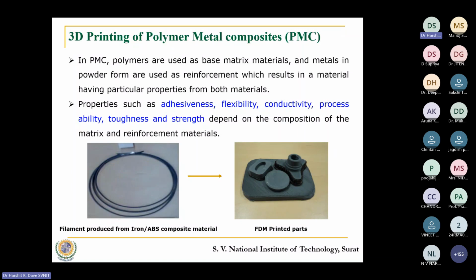Similarly, if we try to go for the SLA process where we select polymer resin and try to mix metal particles, that can be a reasonable option. But because SLA creates layers of a very small thickness, say 10 microns, 20 microns, the particles that we may require have to be nano size. So the process becomes slightly costly, and maintaining them in even proportion also becomes a tricky task. So when we talk about metal particles mixed into polymers, we largely observe that people go through the FDM route.